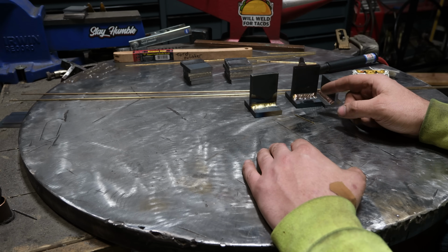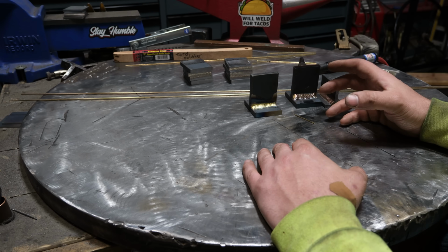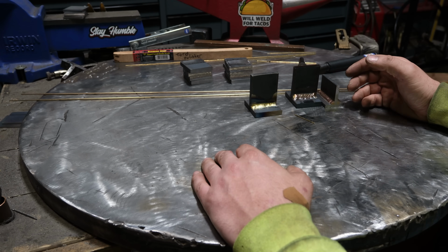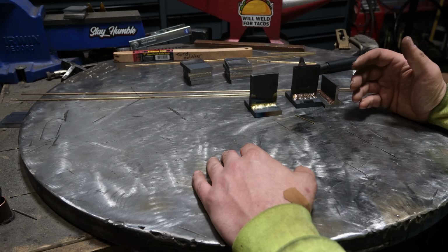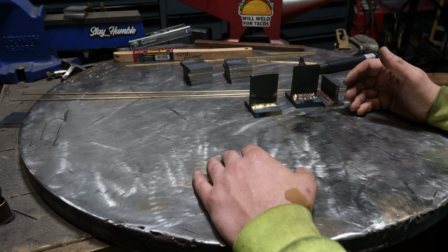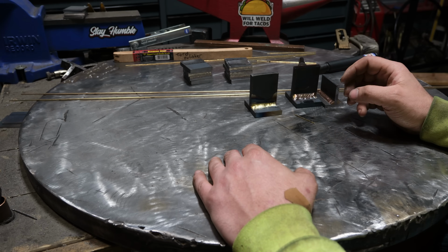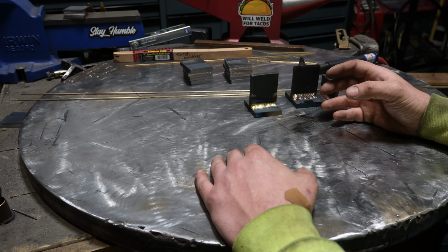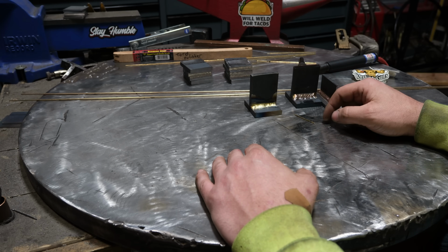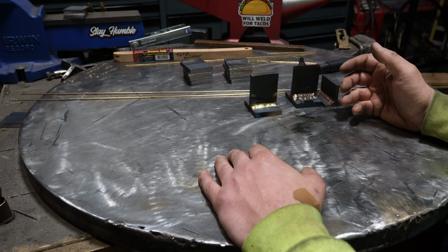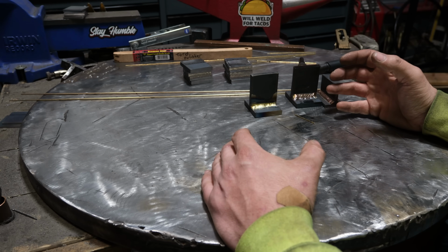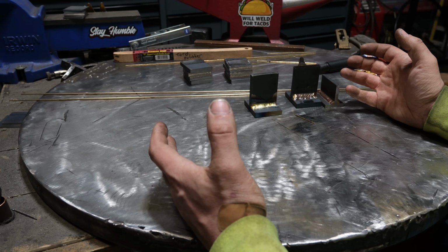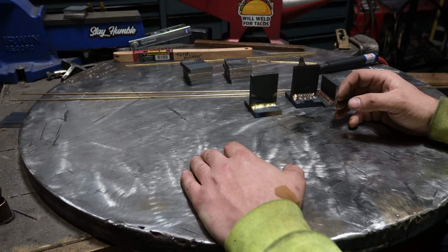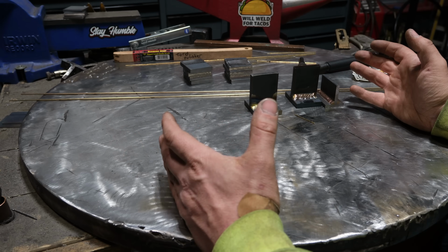You can also braze cast iron, and it's incredibly strong in many cases, which is a great tool to have, because you guys got to remember with cast iron, some forms of it simply aren't weldable. Even with high nickel rods and preheat, they just don't take to welding because of that high carbon content. And since you're not melting the base material with brazing, you can often join two pieces of castings together and not risk cracking, because again, you're not mixing all of those alloys together that don't want to be mixed.